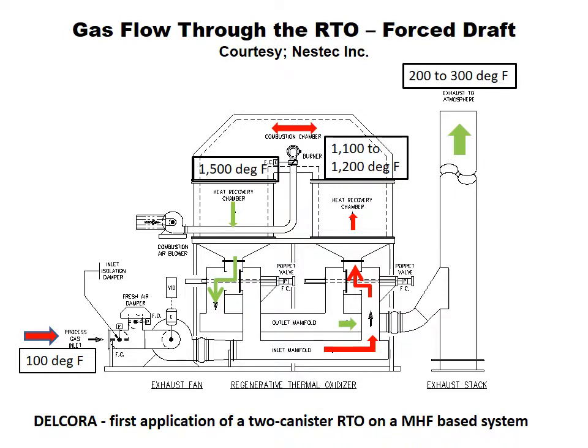You really don't get penalized in fuel very much for temperature on this thing, because it leaves the heat behind. This poppet is over in this position. The gases go down this way and out the stack. After 90 seconds, these switch, and the incoming gases go up this way and go down that way. One way to explain this in terms of fuel is if you think of it like a pendulum. If you get a pendulum and you drop the ball, eventually that settles down. Well, this is like a pendulum, but every time it hits this point, it gets a little kick. So that pendulum swings all the way, and it's remarkably accurate in real-time operation.